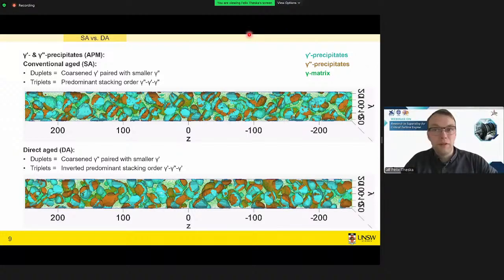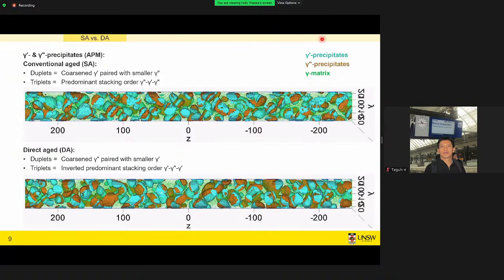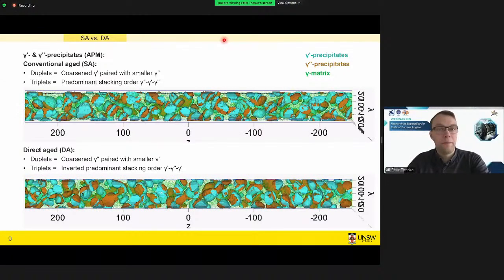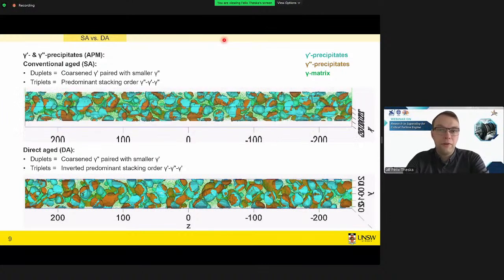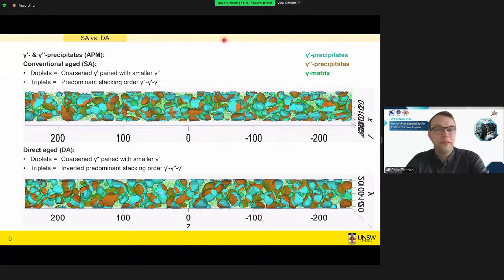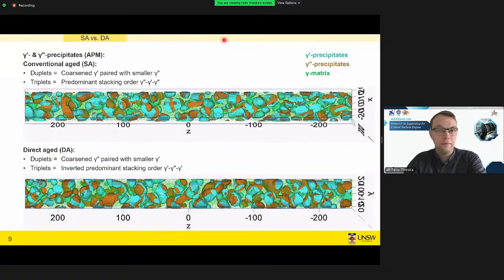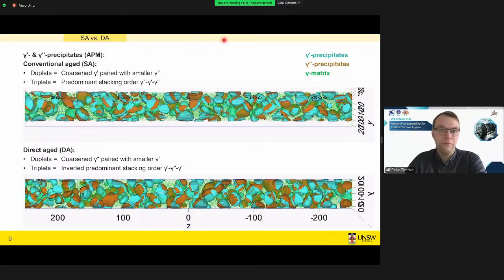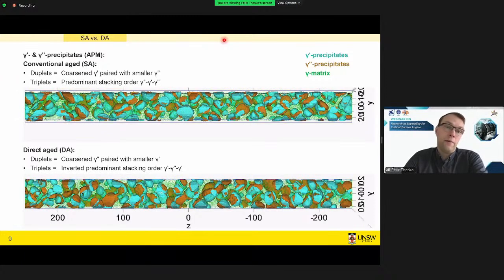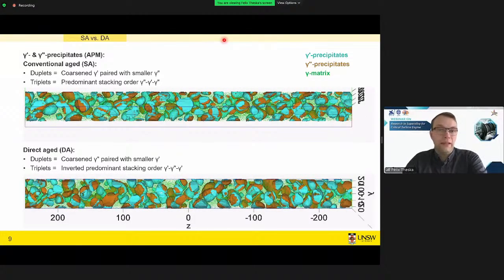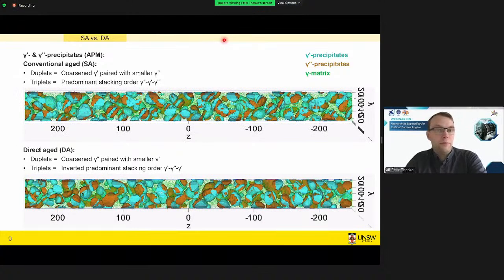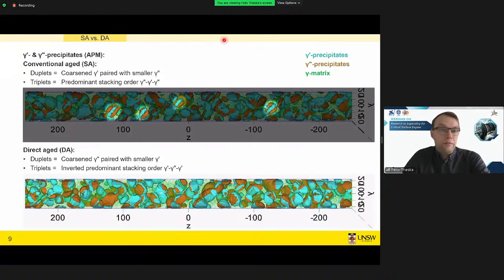So if I move on, on the top-hand side, we see a conventionally processed alloy, which is solution treated and aged. And as we let it rotate, we see that these 2 nanometer scaled particles actually occur together. So we see a gamma prime and gamma double prime sit together. And if we look in more detail at, for example, the duplets and triplets, we find that gamma prime likes to sit in the center of these particles, or is the larger part.